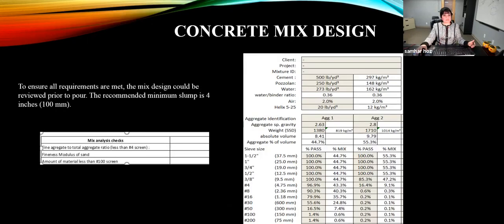All right, concrete mix design. As I mentioned before, Helix doesn't require any change in mix design. We do recommend a minimum slump of 4 inches, typical mix. However, we can run mix analysis if we can get the mixing proportions for your mix, along with sieve analysis. Then we can run a quick concrete mix analysis with Helix dosage, but typically it doesn't require any change in mix design.